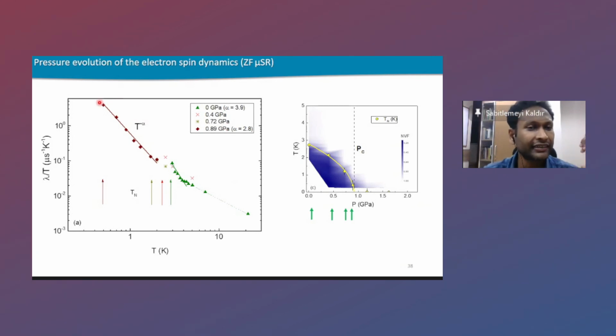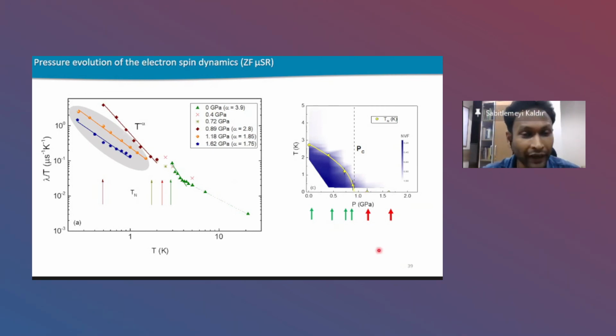You see that there is an ordering at around 350 millikelvin. And you see, of course, there is a critical divergence of lambda over T. So now the question is, what is happening beyond the quantum critical point? To our surprise, what we have seen is the data taken at 1.62 GPa and 1.18 GPa, where 1.62 GPa is almost 1.75 times the quantum critical pressure. Still, we see some divergences of lambda over T. And that is actually very surprising.